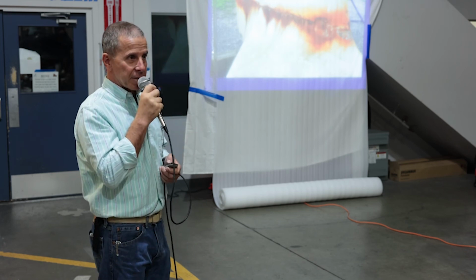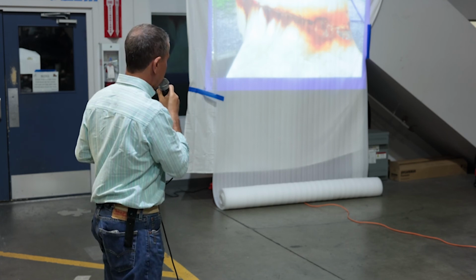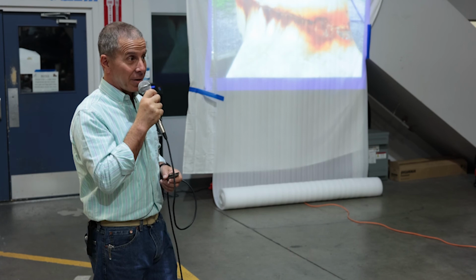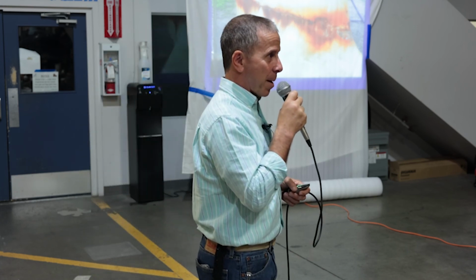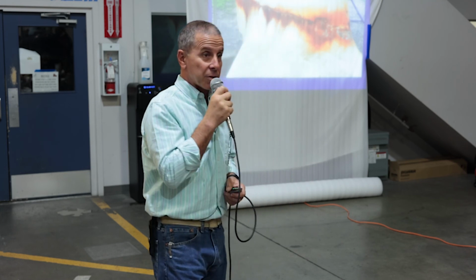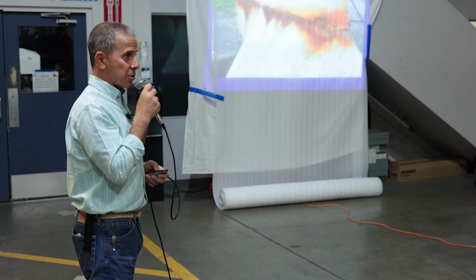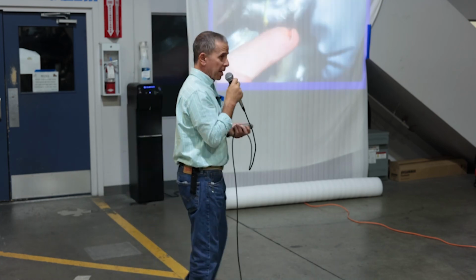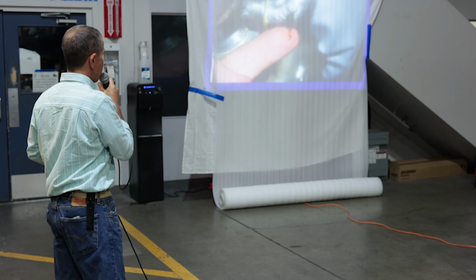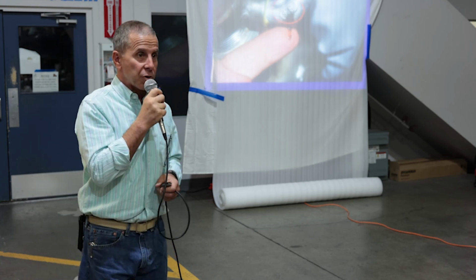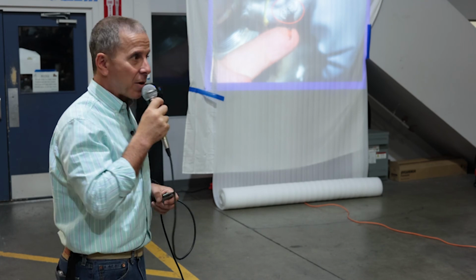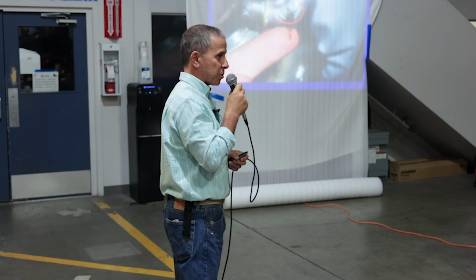A keel example in this case that uses stainless fasteners, that water leaked into that interface between the two, and that brown staining is a pretty aggressive or blatant example of this. All that brown staining that you see there is an indication that crevice corrosion is going on in a pretty big way and should not be ignored, especially in a high stress scenario like this. Now, even the highest grades of stainless steel can be susceptible to this. If you look closely at this, you can see that it's labeled 316, which is one of the more corrosion resistant versions of stainless steel. But if you rob it of oxygen, again, it is going to eventually suffer from this scenario if it's exposed to water as well. So sometimes there's not a good solution to this.